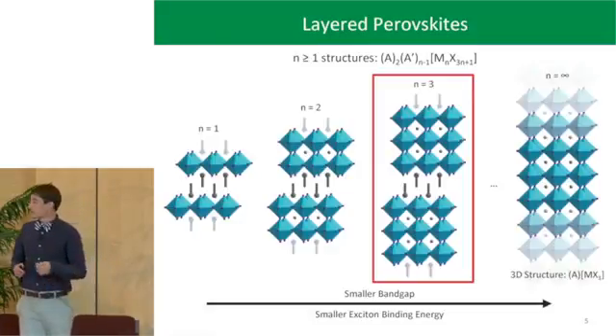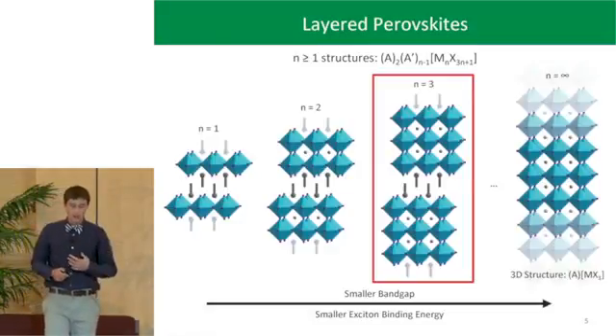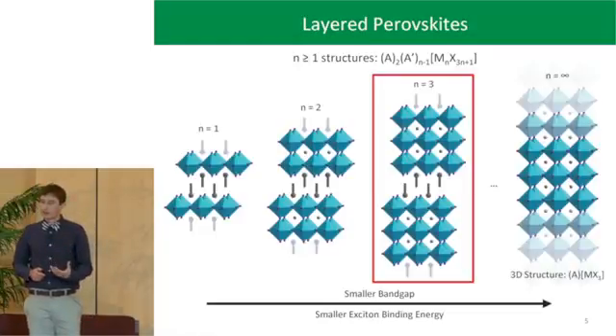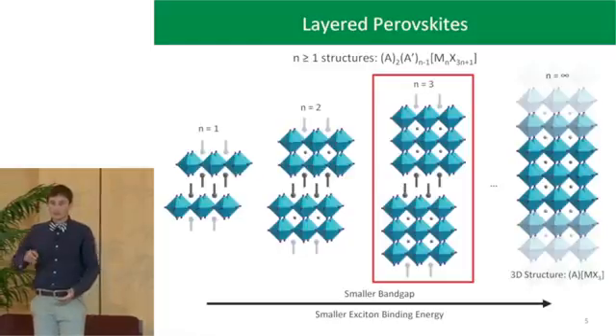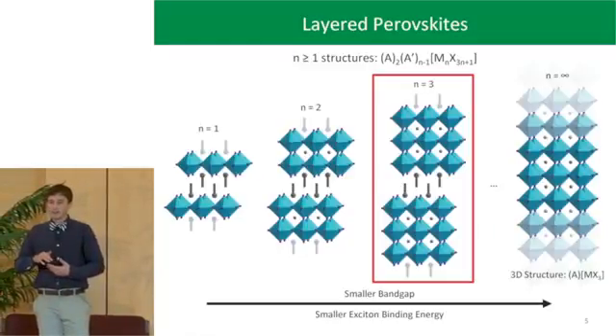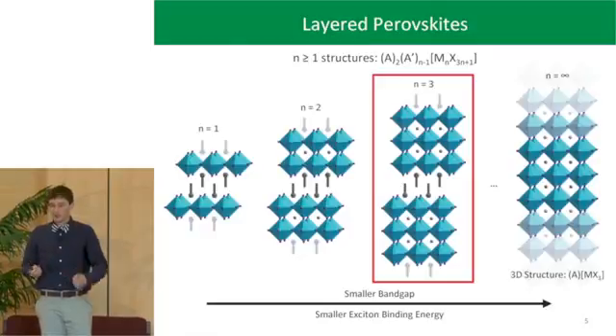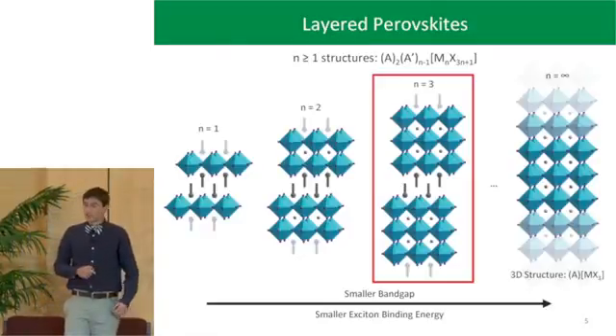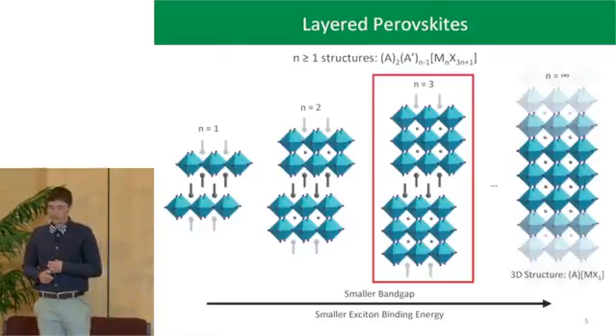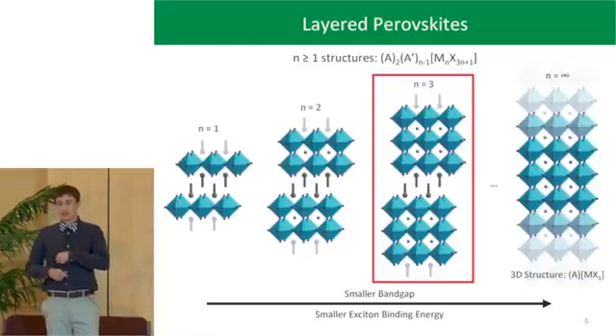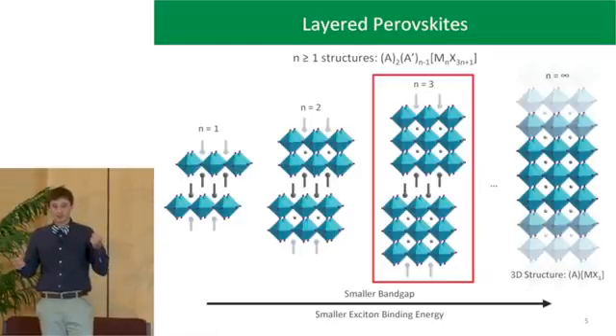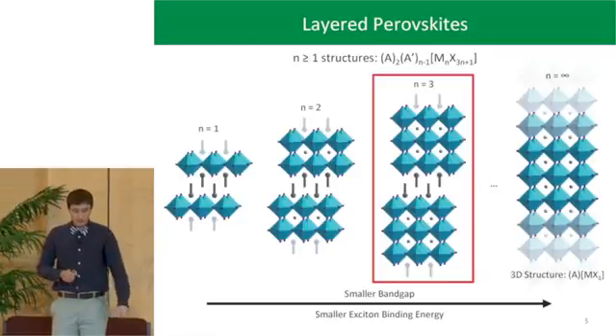For example, something very important to solar cells are the band gap and the exciton binding energy of these materials. As you go to smaller N values, you're reducing the dimensionality and therefore reducing the size of that box. And you're increasing the band gap of the material. Also, the exciton binding energy increases. So therefore, when you create a hole and electron pair in the material, it's much harder to separate those and do work using the device.